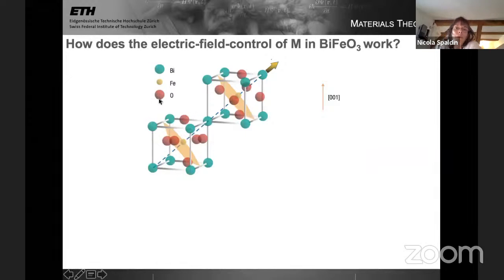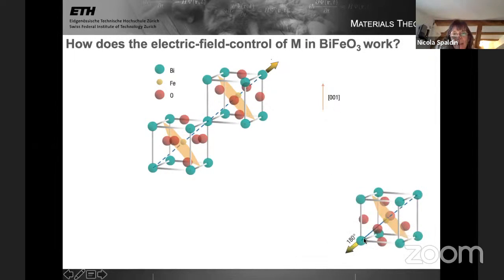So what's going on? How does this electric field control of the magnetism work? Here's a picture of the bismuth ferrite again. It turns out that the electric polarization is in the diagonal direction, the 111 of these perovskite cubes. And the easy plane for the anti-ferromagnetism is perpendicular. It's the 111 plane. So the magnetic moments are lying in this easy plane. It's actually a rather isotropic easy plane. And if I switched my bismuth ferrite, switching the electric polarization from this top right diagonal to the bottom left diagonal, the magnetism would not switch. It would stay in this easy plane, and it wouldn't care. There's nothing symmetry-wise that would even ask it to change. The ferroelectricity would just go in and out the other side, and it wouldn't be affected.